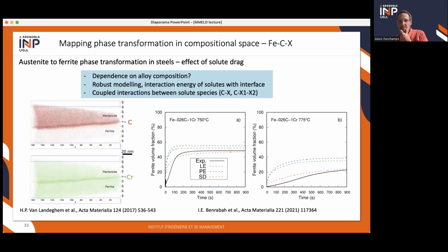The last example that I will develop a little bit more is something we started a couple, 3-4 years ago, on the effect of solute drag on austenite to ferrite phase transformation in steels. And this we look at with high energy X-ray diffraction. So solute drag is the fact that solute is segregating to the interface between austenite and ferrite during the phase transformation.